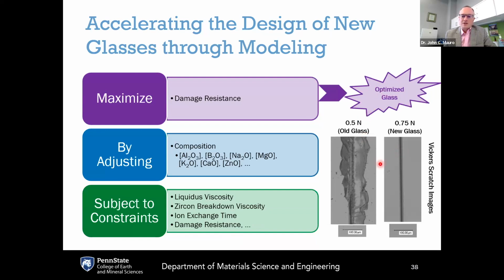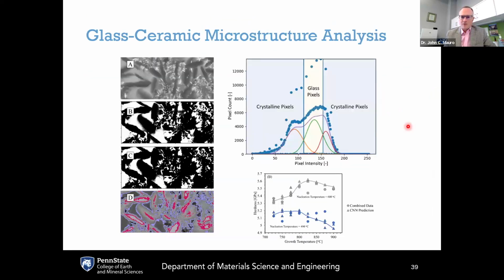This glass went on to sell billions of units. You can see this is the performance of an older glass under a 0.5 Newton scratch, where you can see this lateral cracking, which not only looks bad and feels bad, but greatly compromises the strength of the glass, versus the new glass with improved damage resistance, which is just deforming plastically under the indenter here at an even higher load. Our group is also working on glass ceramics.